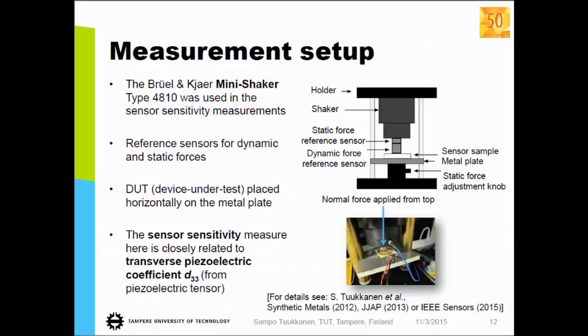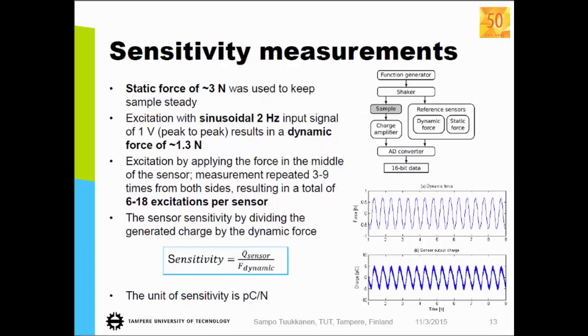And then when we get the sensors made, we used this kind of mini shaker setup where you basically put the sample below the shaker head, and then you can shake it in the Z direction, and you can basically detect the D33 piezoelectric coefficient from the sample.